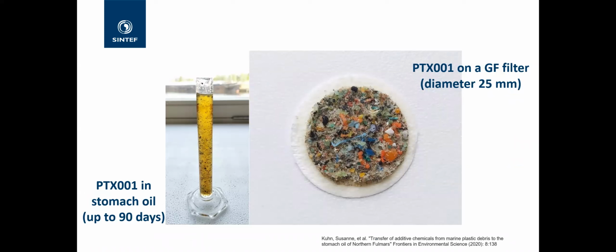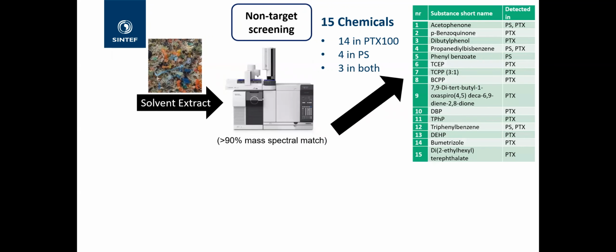So we cryomilled the beach litter and we incubated that with stomach oil from the seabirds for up to 90 days to mimic that length of time that they can be there. And then we did the same approach. We took a solvent extract of the reference material, microplastic reference material that we'd made, so that we knew all of the chemicals that were present. So these were some of the ones that we were able to identify.